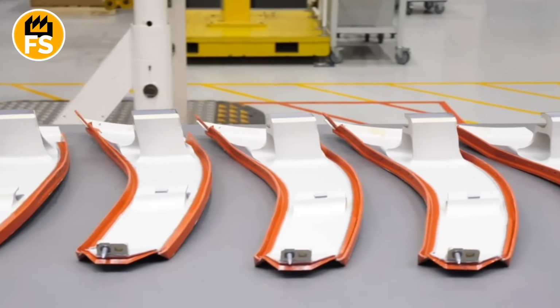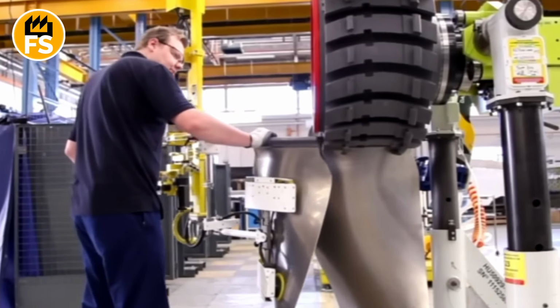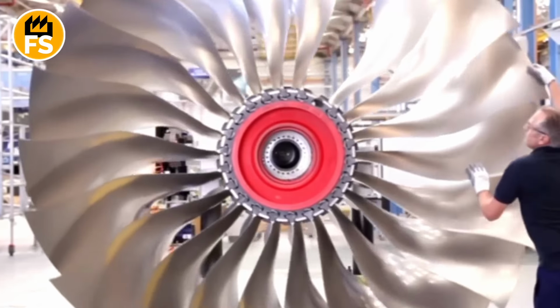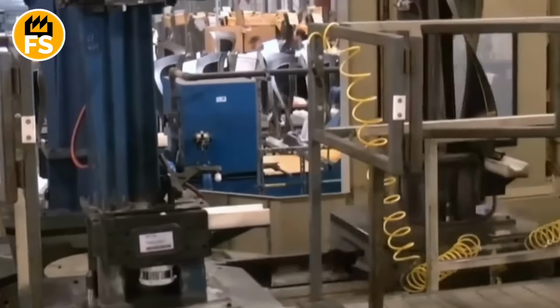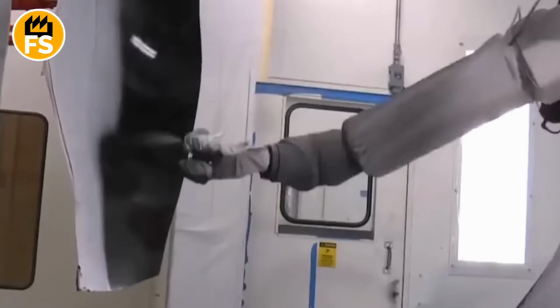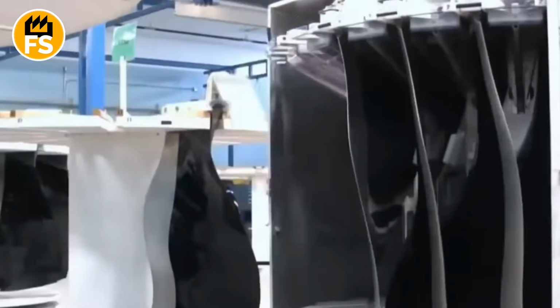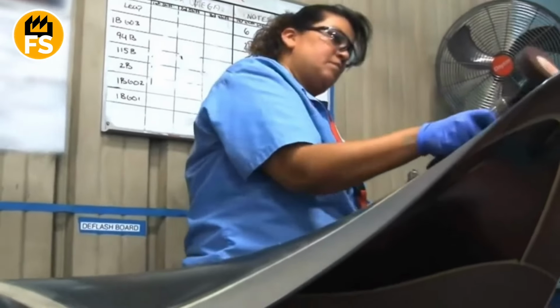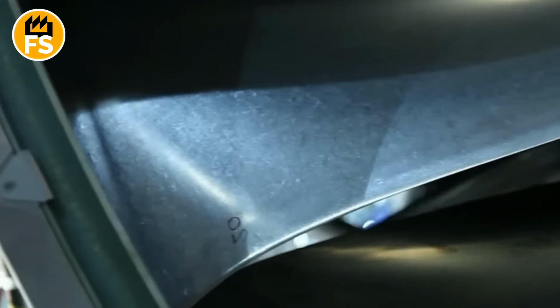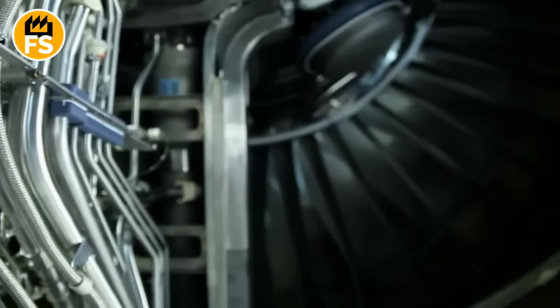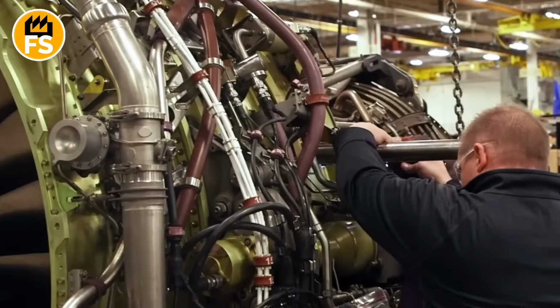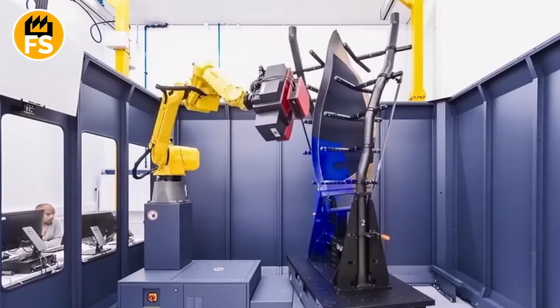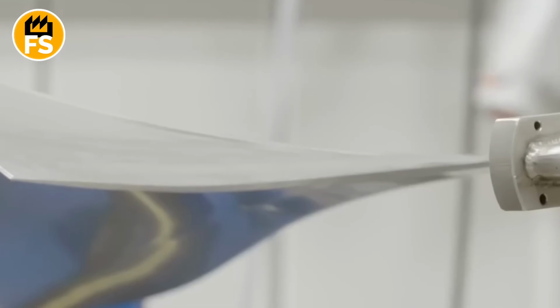Next, the show begins. In a special furnace, superalloys are melted, which include nickel, chromium, and other metals capable of withstanding temperatures above 2,000 degrees Fahrenheit. This molten metal is poured into the ceramic mold. But the secret is not only in the material, but also in the way it's done. To make the blade withstand gigantic temperatures and loads, it is often cast as a single crystal. This means that the entire piece of metal has no seams, microcracks, or different grains, as in ordinary metal. Why is this important? Seams or microcracks in such conditions are like a minefield. One mistake, and the blade shatters.